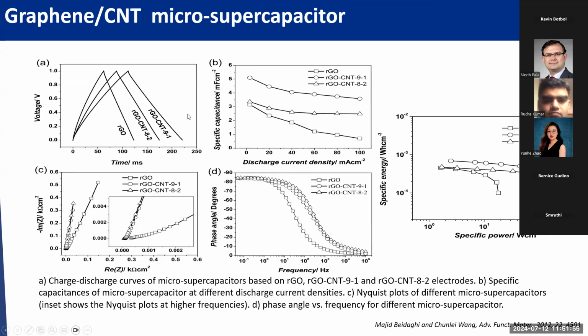And if you look at the charge discharge curve, you can compare and try to draw the Ragone curve to identify the specific power and specific energy. And you can see from the Ragone curve, the RGO CNT with 10% CNT ratio gives the best performance in terms of both energy and power. And from the impedance measurement, we can also identify the time constant, basically at a 45 degree phase angle, where you can measure the frequency. In that case, we found for the RGO CNT composite the time constant, which tells you how fast the charge transfer is, reached about 4 milliseconds.